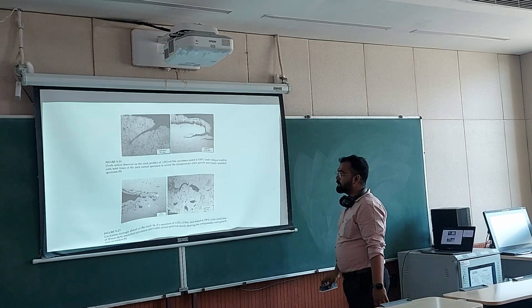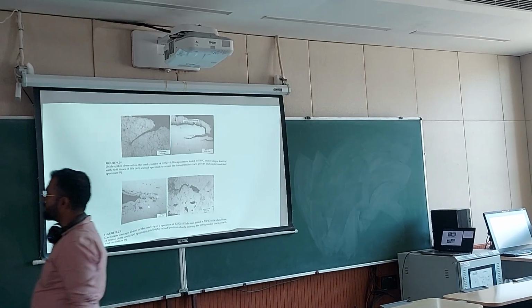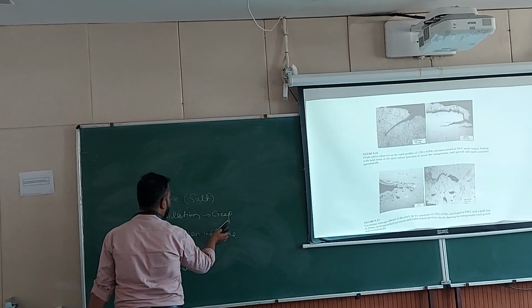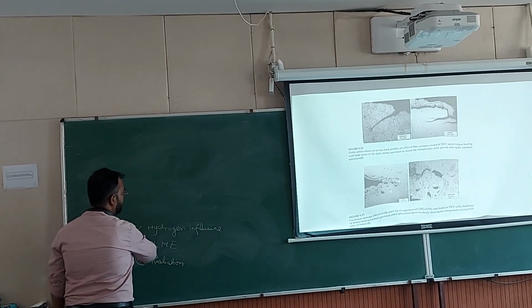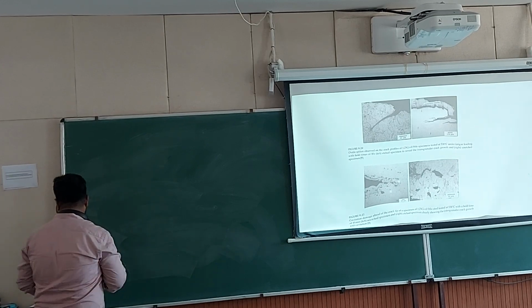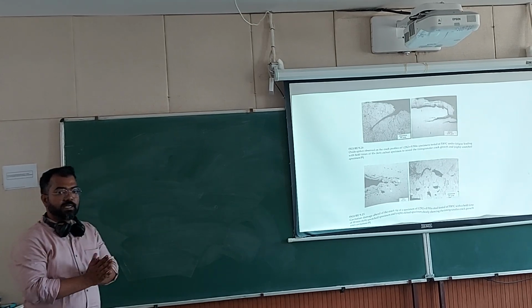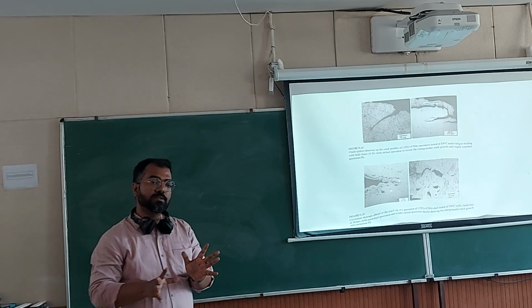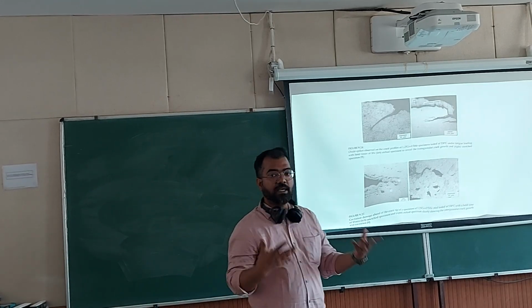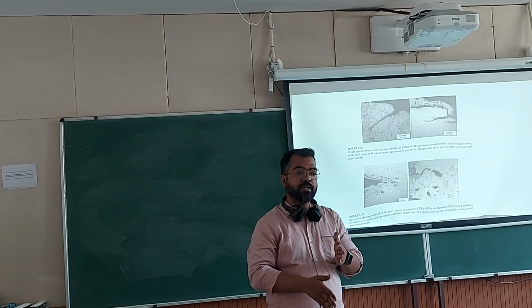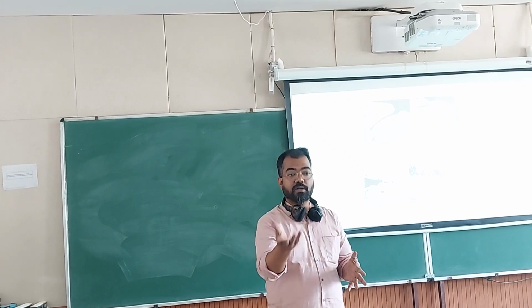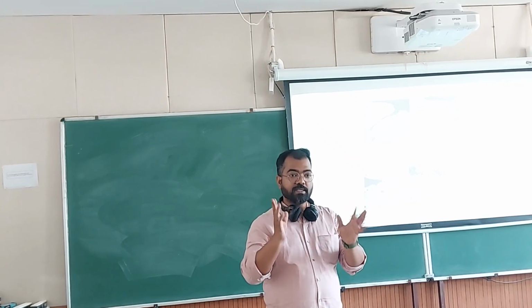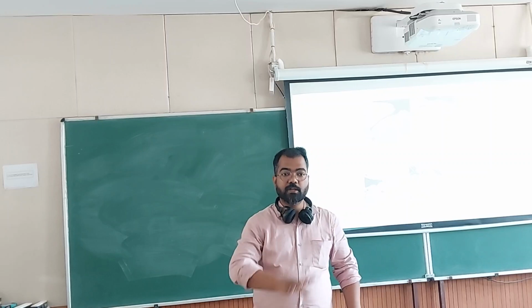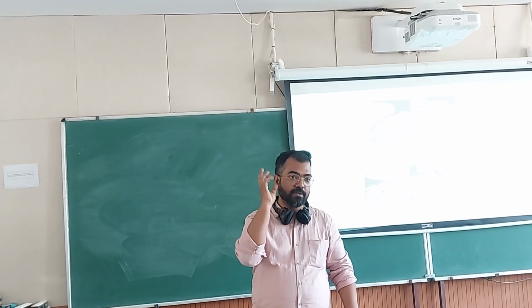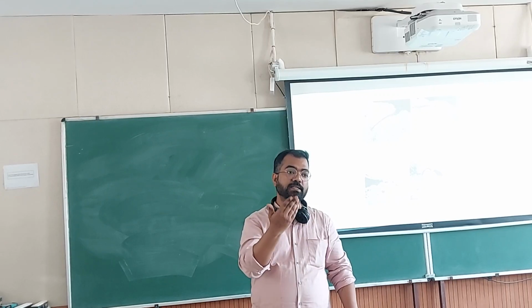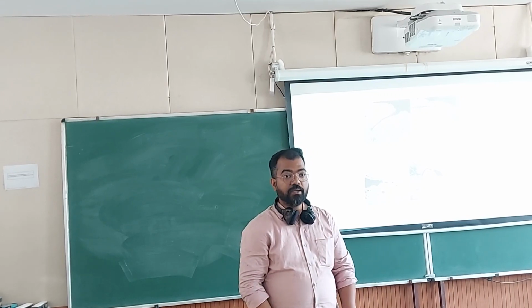After this, let us talk about normal corrosion environment. Like you can have salt environment, chloride environment, sulfide environment, and you can have oxide environment, and in all those cases there will be electrolytic dissolution. When you have a crack you have a highly stressed area, and they will be dissolving it, making the new surface available that will get oxidized, for example. So this oxide will close the surface because oxide has formed and the Pilling-Bedworth ratio is high. So further oxidation cannot happen. Okay, so it should stop.